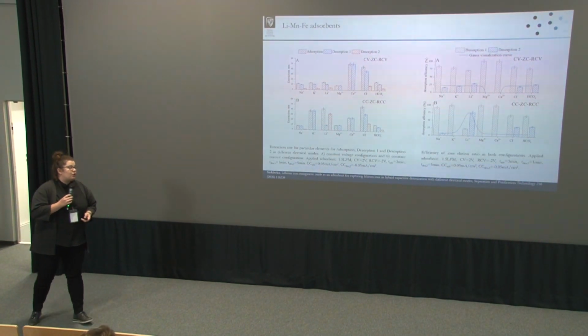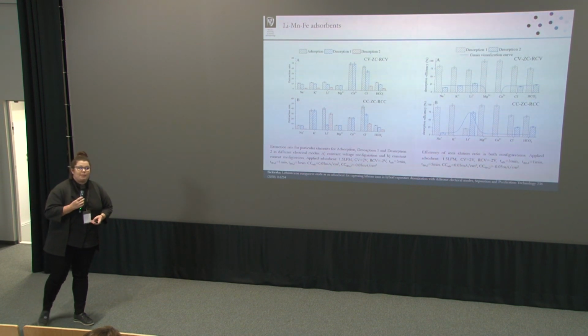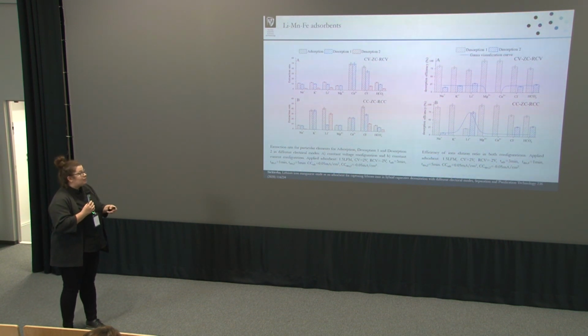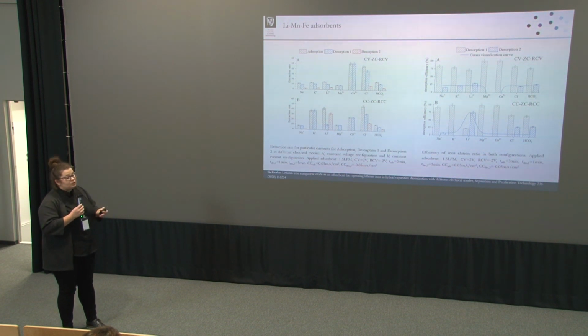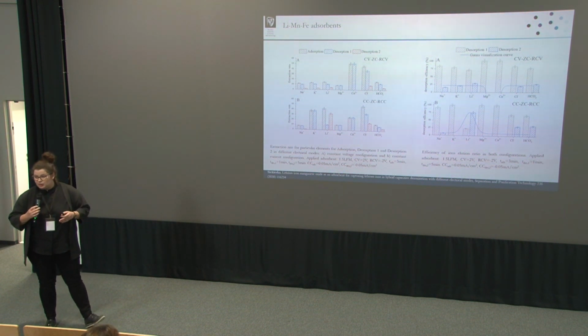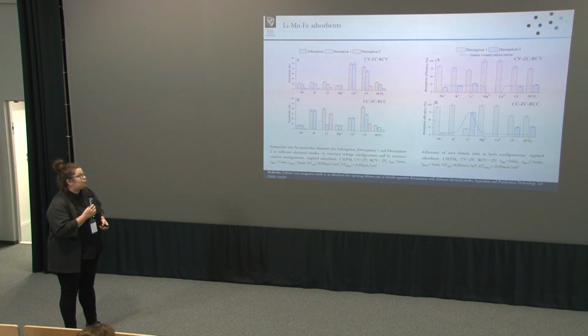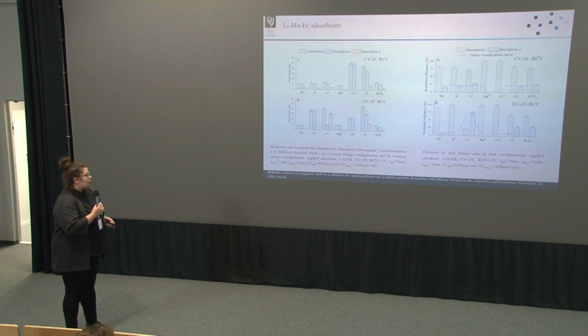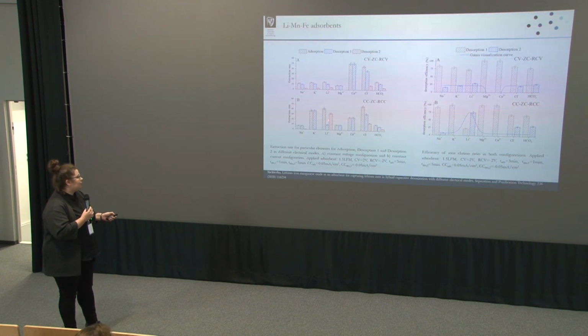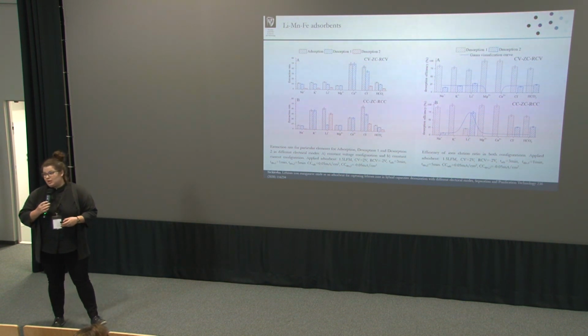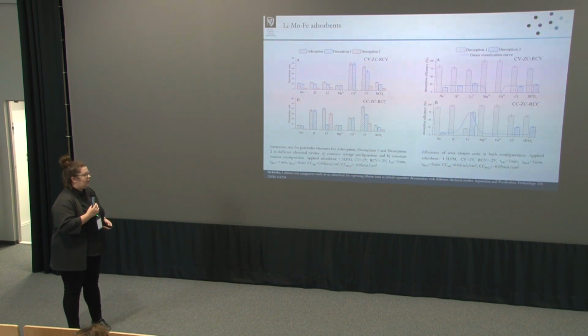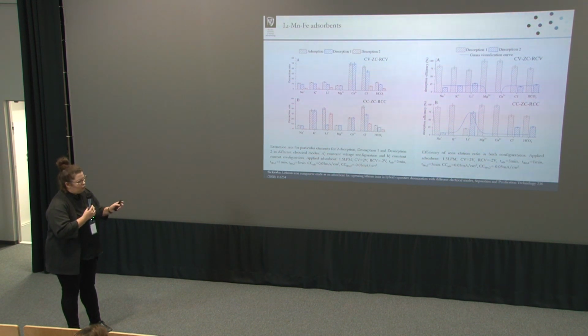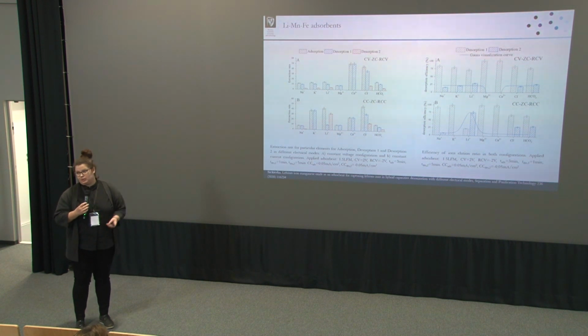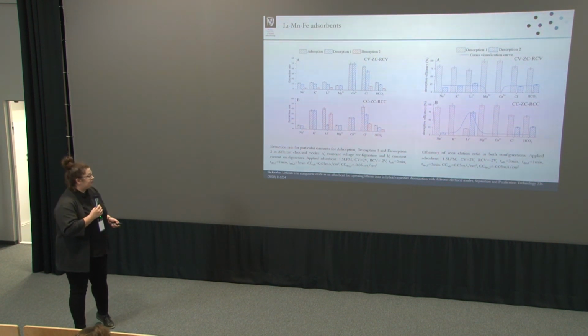This is the research for a different material in terms of the sorbent. Previously it was based on lithium, manganese, and titanium. Here I switched the titanium to iron spinels, and also observed the same behavior. We can find highly selective lithium in the second step of the sorption without almost any other ions. Also, you can see here that almost 75% of sorbed lithium was released in the second step of the sorption.